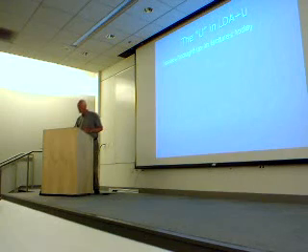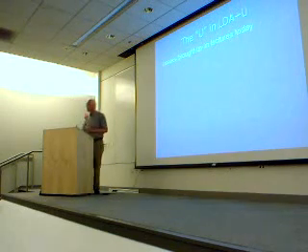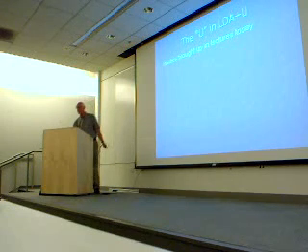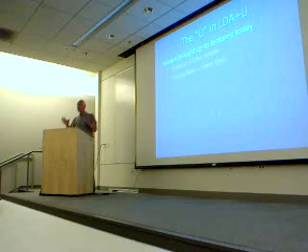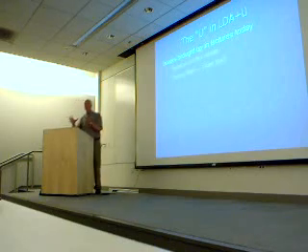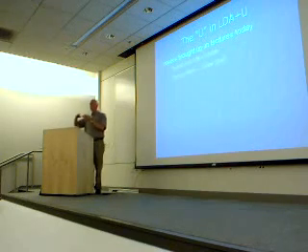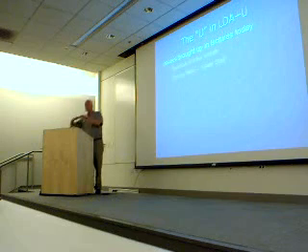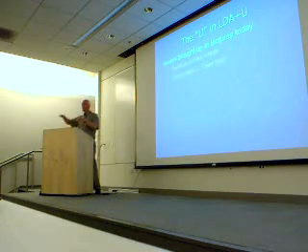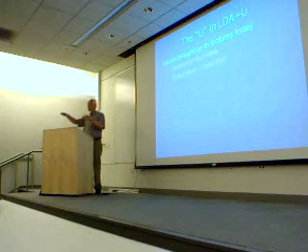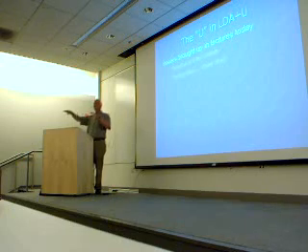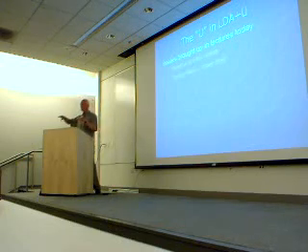Okay, so now what is U? U and LDA plus U, I'm not going to say much about because that's really what was talked about today. So we know that the interesting cases are when you have partially filled shells. That's what the U is doing, is stabilizing the system at one number of electrons or another number, like n or n plus 1. The usual Kohn-Sham density functional theory gives you occupations that are fractional between the integer values.